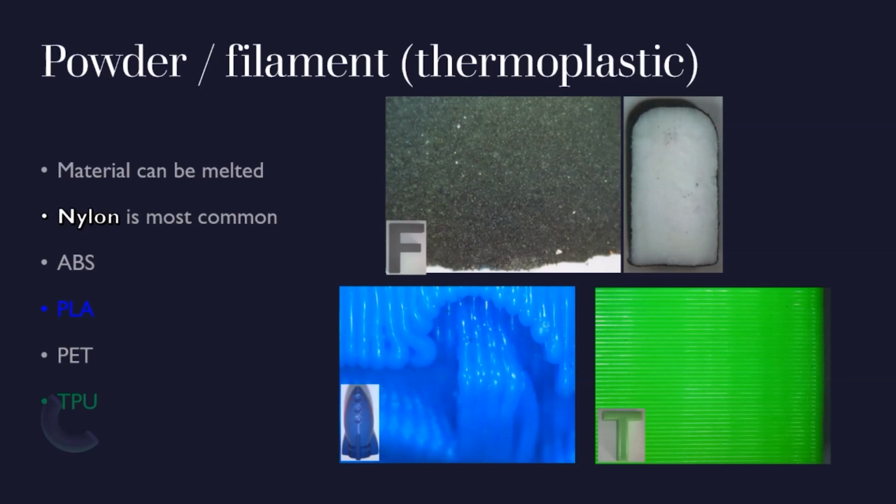Also, under the microscope, I observed that in abraded areas, which likely occurred during shipment, there were some off-white areas peeking through. Given these objects were not art per se, I went ahead and did some destructive analysis and confirmed that indeed the black color was imparted during a post-processing step, as you see from the cross-section of the object.